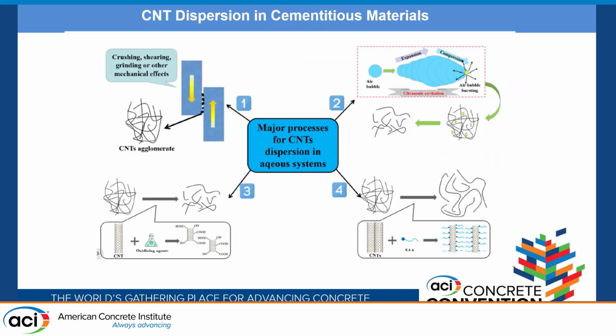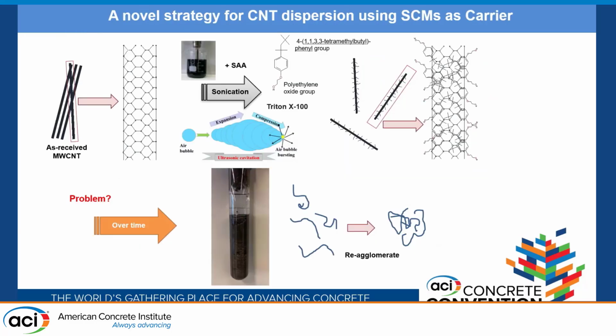So that's the goal. And in that process, of course, the challenge is dispersion. That's something that we looked at first in this research. Dispersion of CNT in cementitious system has been studied for quite a while. There are different ways, from mechanical sonication to chemical. You can do surface grafting or use dispersants to try to disperse the particles. One of the challenges, of course, is that following the dispersion process, to use that in a cementitious composite system, we want to have a stable suspension before that gets mixed with cement. And having a longer storage shelf life is challenging, because those nanoparticles, once dispersed, tend to agglomerate.